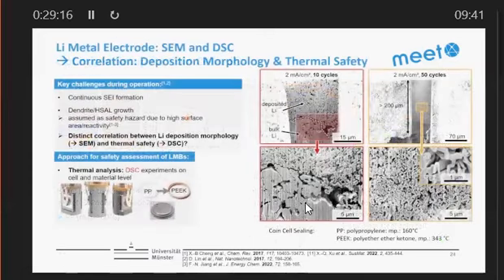So with these three things, we just started the safety test. We took this polyether ether ketone (PEEK) polymer, which allows us to make reproducible safety tests. And we see that after 10 cycles and after 50 cycles, of course, we are having more high surface lithium. So we have a thicker porous layer when we are having more cycles, which is what is expected. And basically, we can also watch this both by cross-section and also with top view pictures.